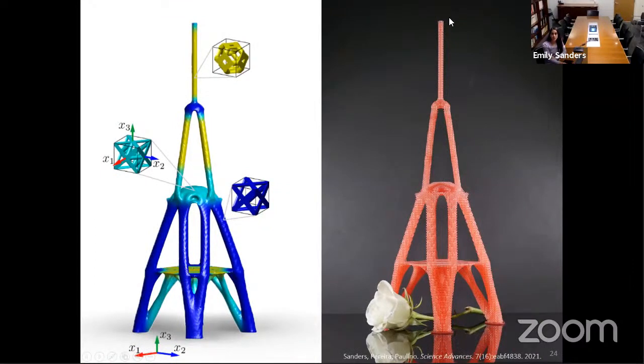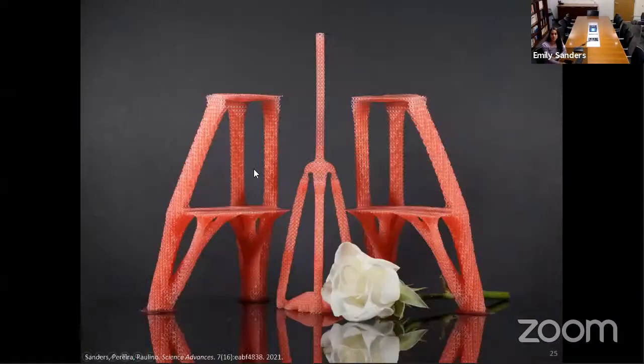This thing was printed at 26.5 centimeters tall, and so that's twice the height that our 3D printer can handle. And so it was actually printed in pieces and then assembled later. This actually highlights the scalability of our approach. So what we did here is we sliced the part for a printer twice as big as our 3D printer, and then we divided those slices into pieces. And because we're working at the slice level, we can theoretically arbitrarily scale the macro scale geometry and keep the microstructures at the resolution of the 3D printer and achieve a really large separation of length scales.